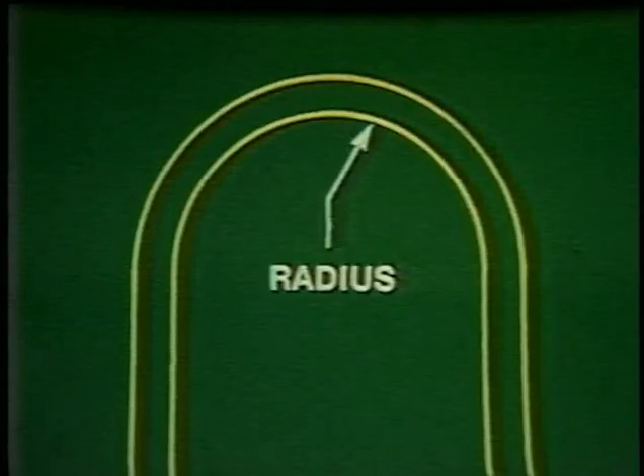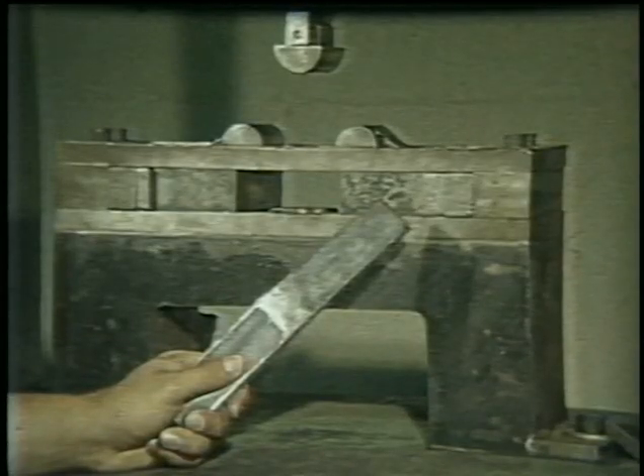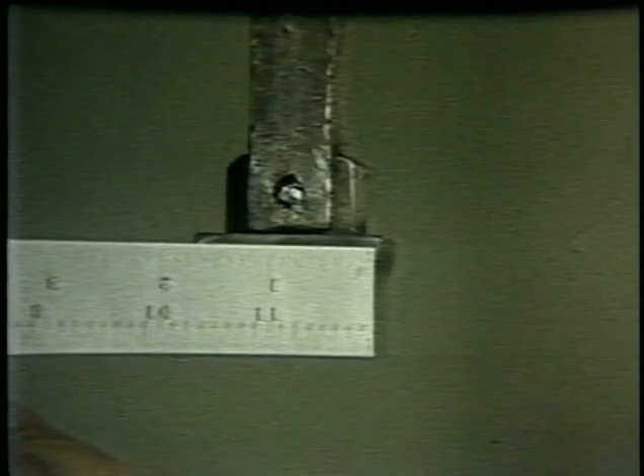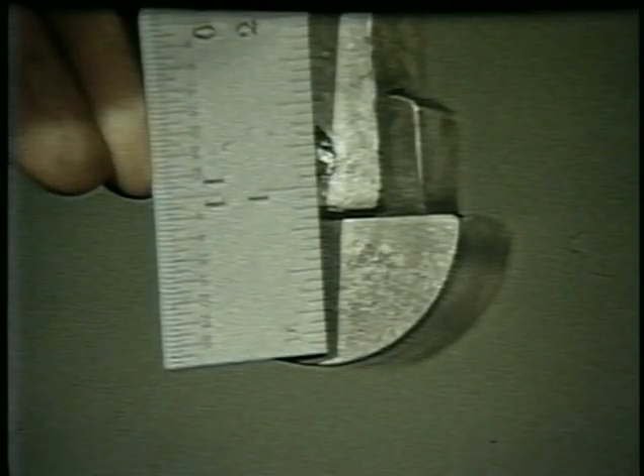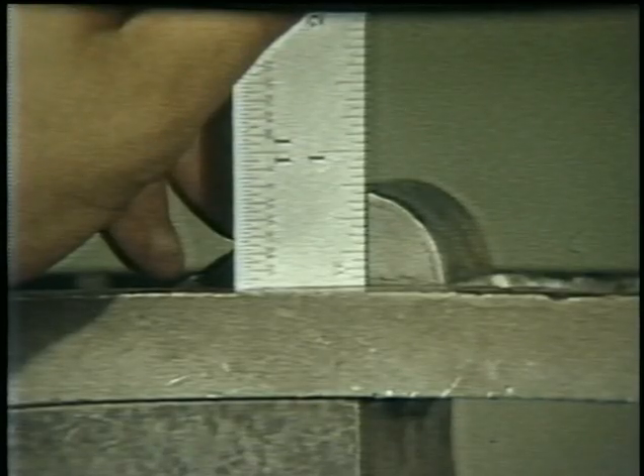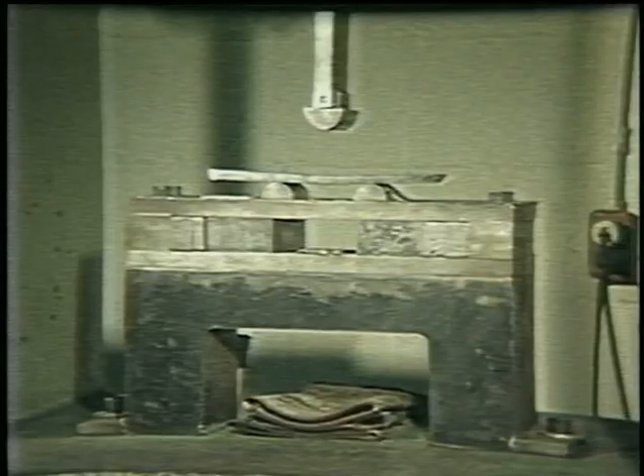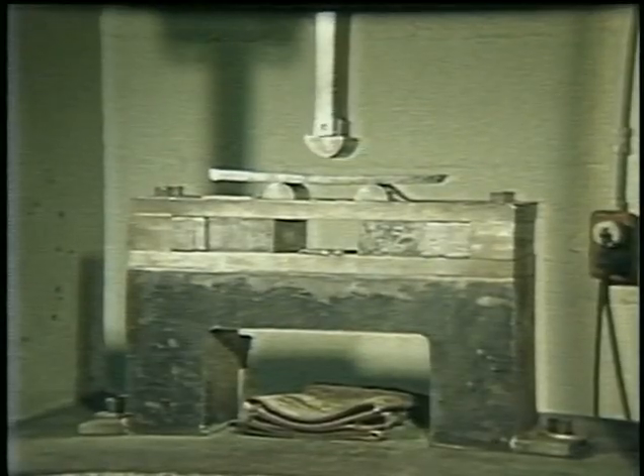Regardless of the type used, the machine must be set up to provide the required radius on the specimen. The requirement will differ with each code, so care must be taken to ensure the proper setup. As an example, a 3/8-inch specimen to be bent on the conventional plunger and shoulder machine would require these dimensions for proper setup. The plunger should be 1½ inches wide. The radius of the plunger is 3/4 inch. The width between the shoulders is 2 3/8 inches. And the shoulders are to have a 3/4 inch radius. When the specimens are prepared, they are placed on the fixture with the weld centered over the open space between the dies. The plunger is then activated to bend the specimen.